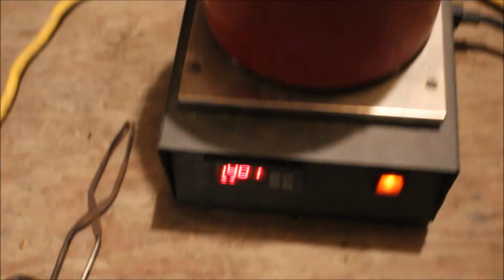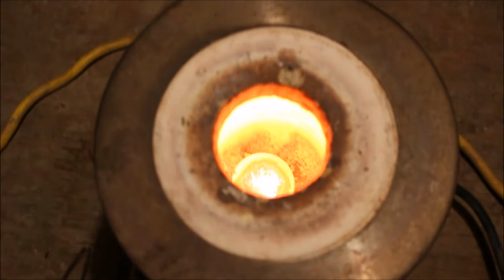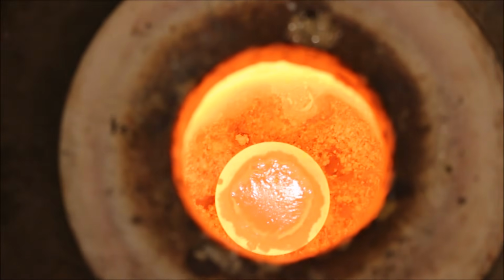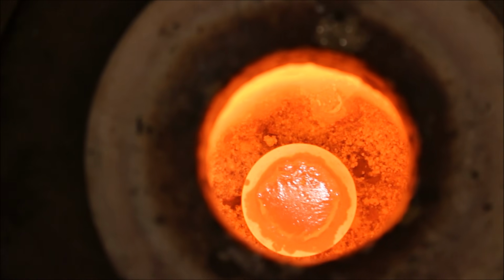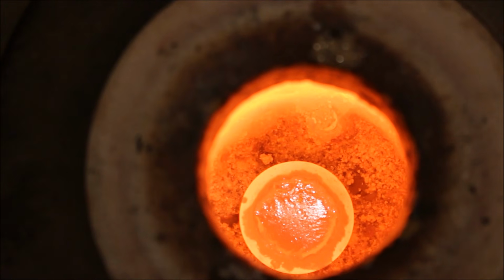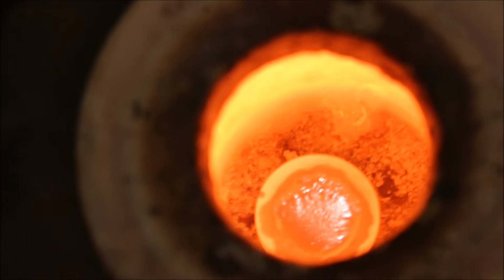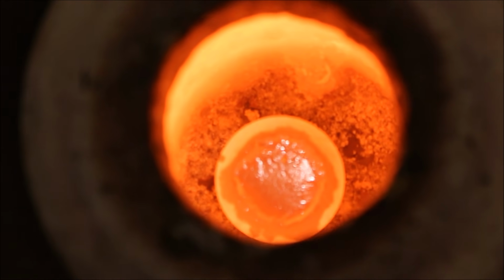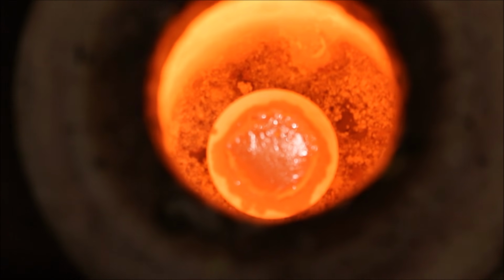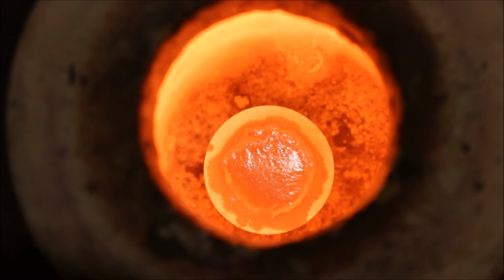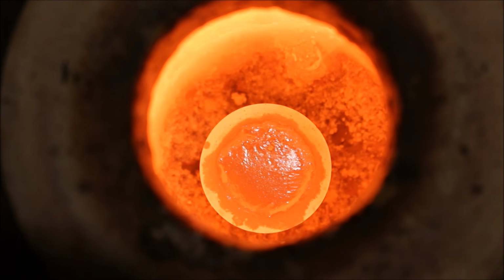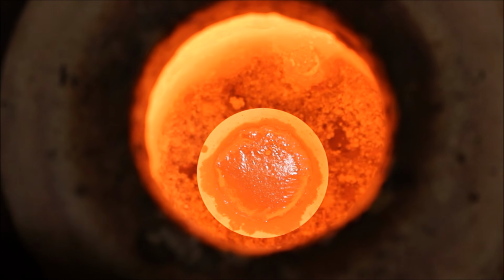Just past 1400 degrees, the lead is melted, but the oxide is not quite yet. Although it looks like the cupel's starting to suck up some of it. You can see there that the cupel's starting to turn red as it absorbs the lead oxide.